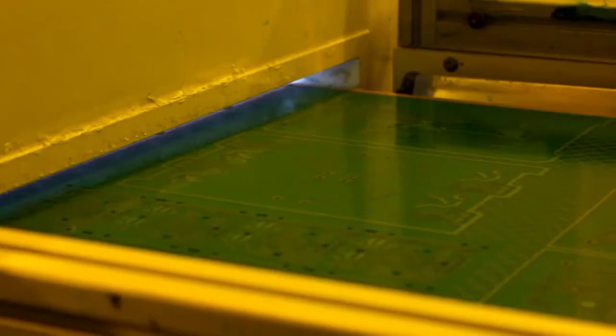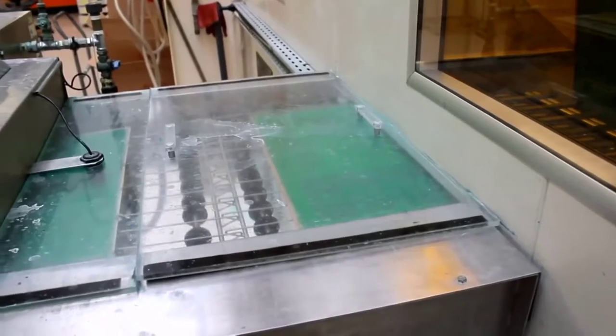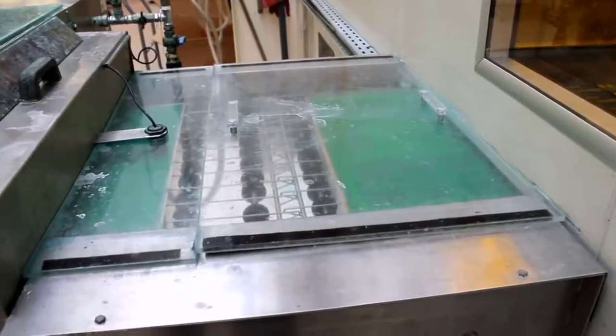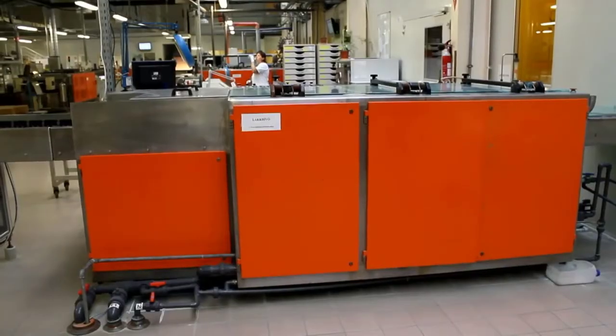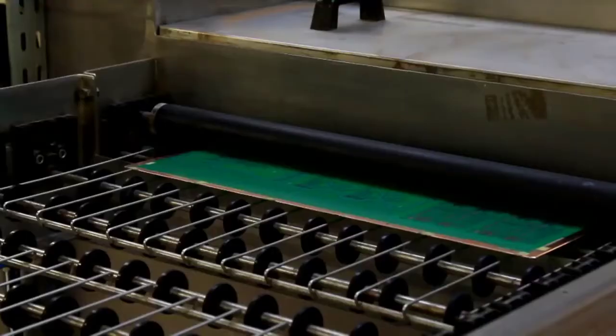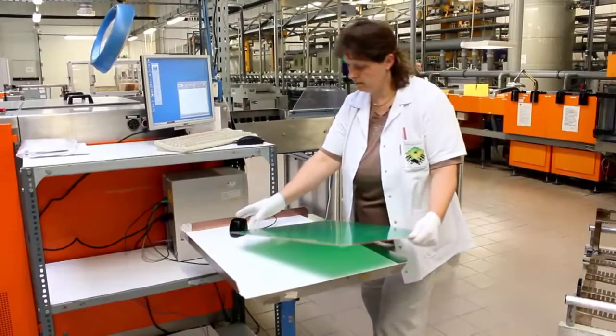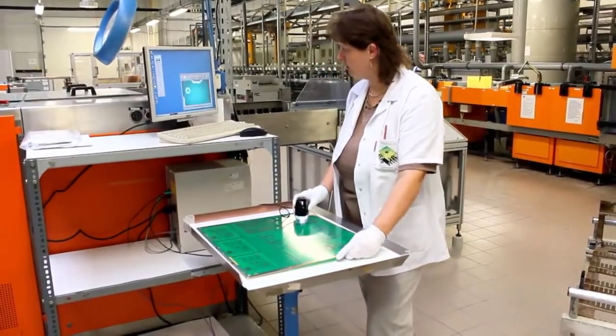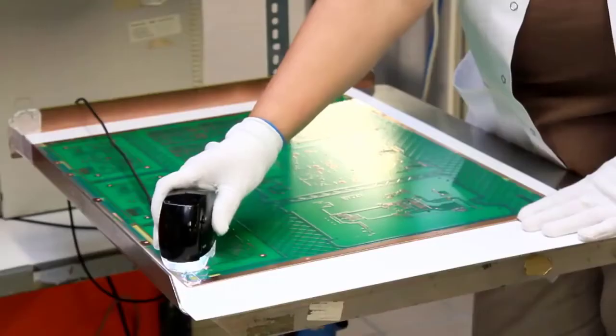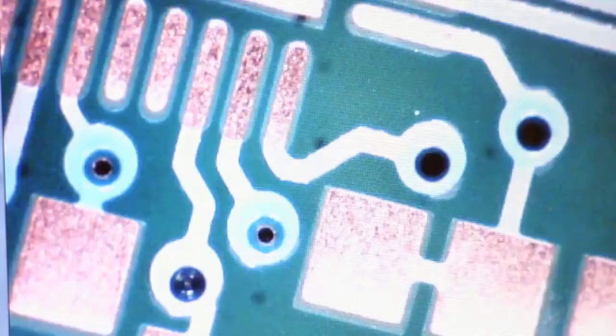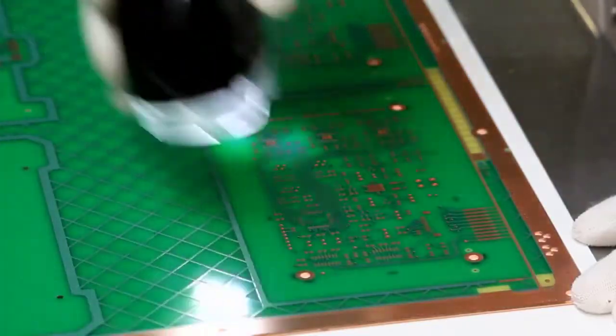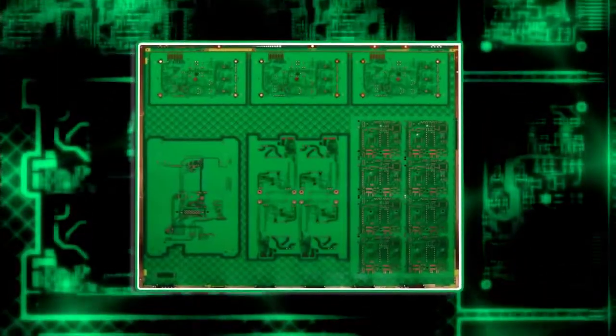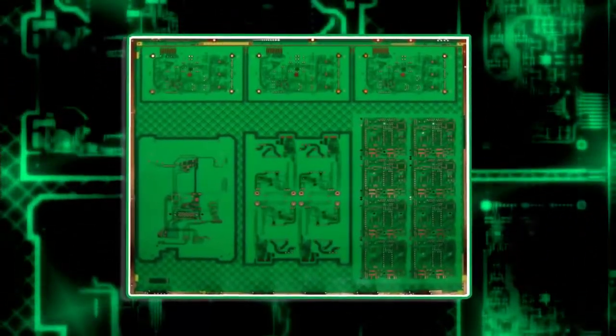The imaged panels are put on a conveyor out of the clean room and into the developer, which strips off the unhardened and unwanted resist. Later, the required resist will be further hardened or cured to provide a robust and permanent coat. For this, we use a conveyorized oven in the same way in which the boards were previously tack dried. But first, the operator checks the alignment of the solder mask on the panel and makes sure that there are no traces of ink on the pads or through the holes. Even slight traces will compromise the solderability of the finished PCB.